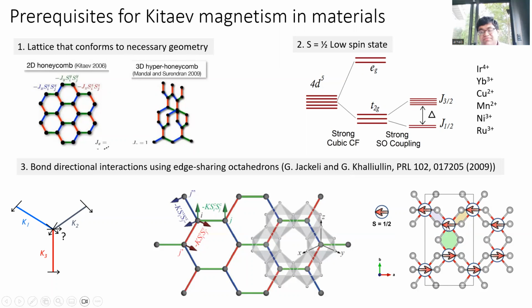So essentially, if you look at it, these are the cations, which are the spin halves, and these are the anions. And if you have an octahedral cage, you will have 3 bonds which will face 3 different directions, and the Ising interaction will be along those bonds. So you can see that here the cation and anion form these tiny squares. This is a square, that's a square, that's a square. And each of the squares faces a different direction. And it turns out, because of the Goodenough-Kanamori rules, the Heisenberg interactions cancel out, and your Ising interactions basically come perpendicular out of these 3 squares. So that's how you produce the Kitaev interactions.